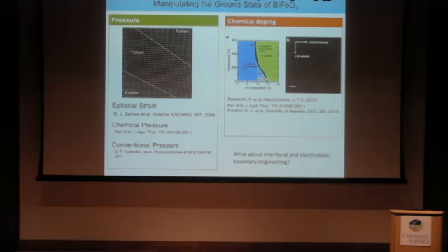The important thing for what I'm going to talk about is that I'm going to mention magnetism a bunch, because I do neutron scattering. Through this whole phase region, as far as we know, it's a G-type antiferromagnet, where in the thin film case you kill the cycloid for most strain states. It's just a normal G-type, but the tilting patterns are different going from the rhombohedral state to the orthorhombic state.